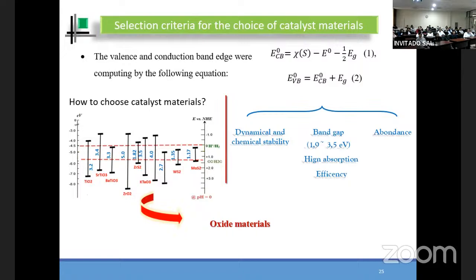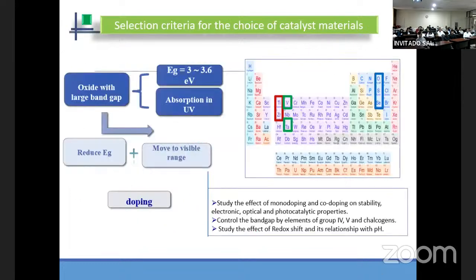And when we apply this DFT to our compounds, like perovskite, for example, we have a problem for this material, like titanium oxide. We have a band gap, but the band edges are not the good values for photocatalysis, or the band edges are not localized between these potentials. So how can we adapt any material to be applied for photocatalysis application? As a first idea, we can dope this material with some elements, and we can control the band gap with these elements.